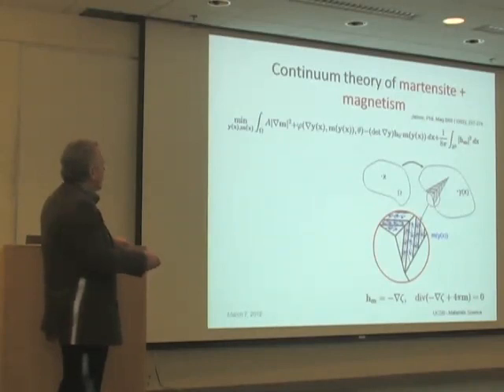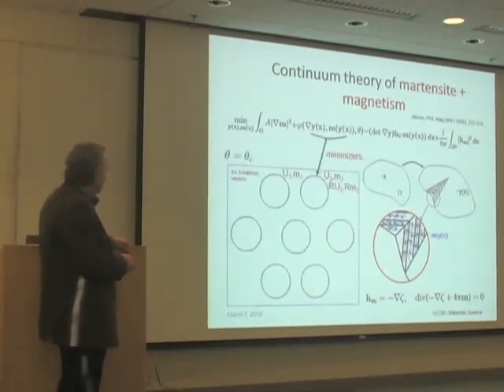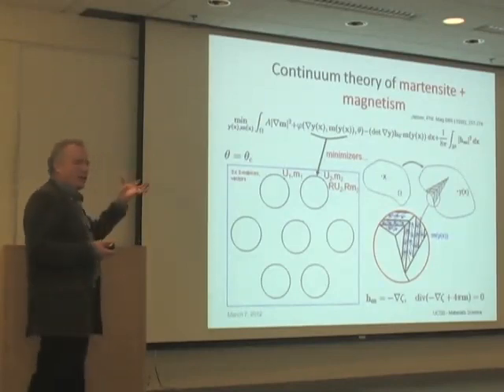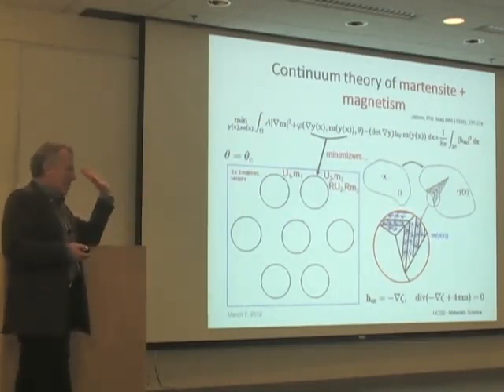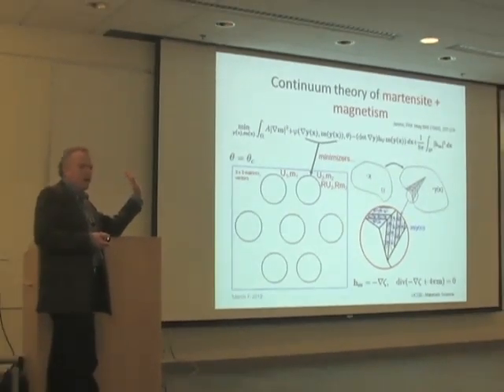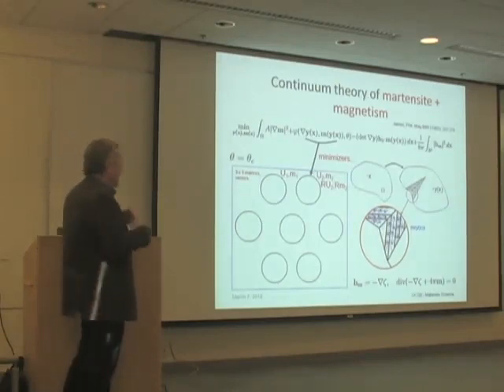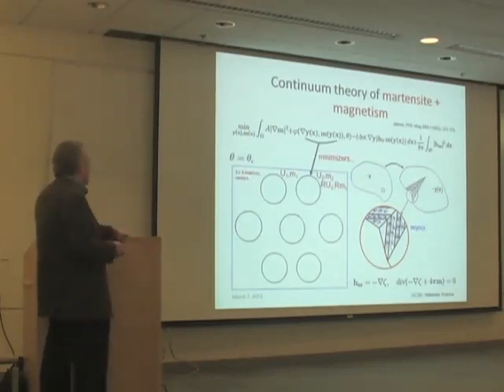And most importantly there's a free energy which depends on magnetization, temperature, and deformation gradient. So I'm using a large strain description, and that's critically important here, actually. It's important to model the geometric changes in the lattice with perfect accuracy and not use linearized strain. Okay, so if you don't know what that means, it doesn't matter. But anyway, it's important on the technical side.